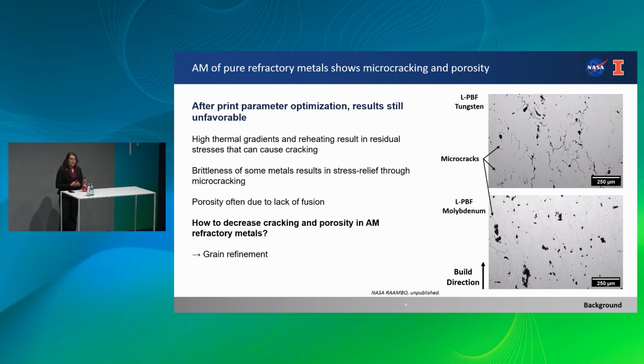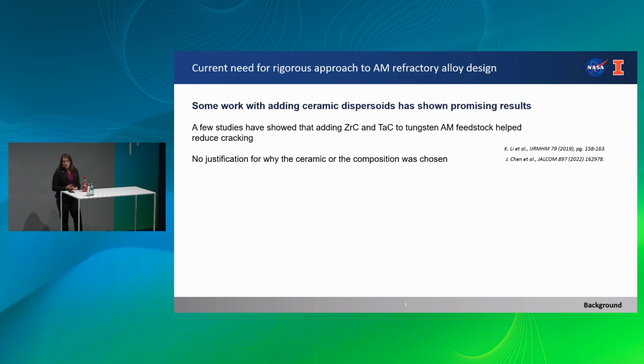And one thing that we've come across in the literature is using grain refinement techniques. A lot of the literature thus far hasn't really gone super into depth as far as a design or an approach to adding these nanoparticles. So some work has found that adding zirconium carbide and tantalum carbide to tungsten helps reduce cracking, but there's no great justification as to why they chose the compositions they did. They only looked at one composition, actually. And so our thought is that we need a better way to design these refractory metals and decide how much these potential nanoparticles could be helpful. And the studies I'm talking about are cited up here.